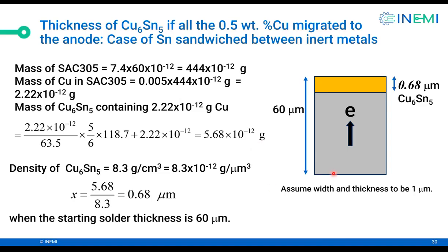Okay, this is an important chart. What this is saying is, if the electrodes were inert, did not metallurgically interact with the solder, didn't form intermetallics, then if all the copper migrated to the anode, how thick would it be? It would be only 0.68 micrometers thick. So there is not much copper in the SAC solder to give you any effect of growth of Cu6Sn5. Not enough Cu6Sn5 grows if the top and the bottom terminals are inert. In other words, the terminations do not interact with the copper. So my point is there's not enough copper in the solder to give you any significant amount of Cu6Sn5. So the copper has to come from somewhere.